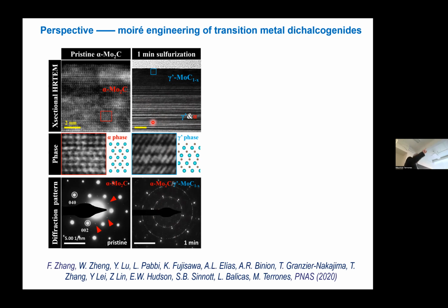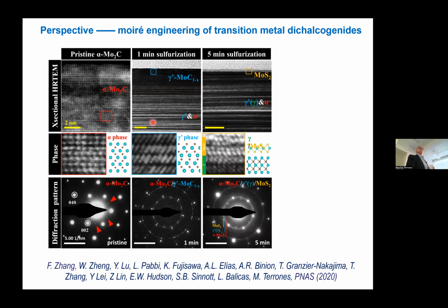So what we think is happening is that for some reason the sulfur is really going in there in between, and it's changing the carbide into a high strain carbide. After 5 minutes, we can start seeing the molysulfide layers here, but we can also see a few layers in between.